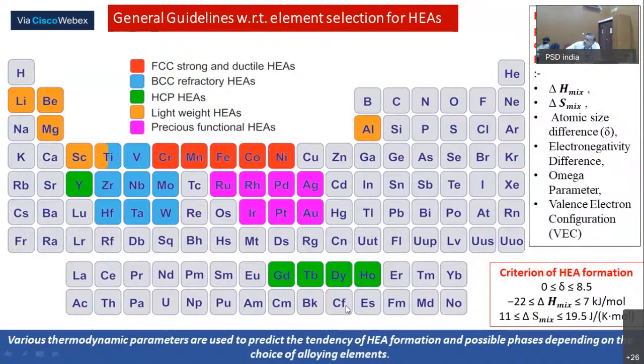Now in the HCP structure, if you look down, you will find that most of the elements are coming from the rare earth series of elements, gadolinium to holmium and yttrium and all. The idea is, if we have these alloys, they can show very high magnetic property, very hard magnets they can make. So there are many possibilities. Among them, if you look around the middle of the table, which is showing the sky blue color, you can see zirconium, niobium, molybdenum, hafnium, tantalum, tungsten, vanadium. These are the BCC refractory metal alloys. This is our point of attention here.